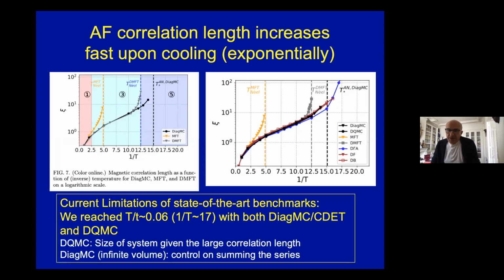Okay, so an interesting point here is that, of course, we expect that at low temperature, from general considerations on thermally disordered antiferromagnets, the correlation length grows exponentially as we cool down. But you see that this growth of the correlation length actually takes place way before, already within the metallic phase, presumably, and approximately also exponentially, perhaps with a slightly different rate than in the regime where there is a charge gap. In fact, it looks like the metallic regime is pretty resilient to the fast increase of the correlation length. You see that you remain metallic up to a correlation length of order 10 or so in units of the lattice spacing.